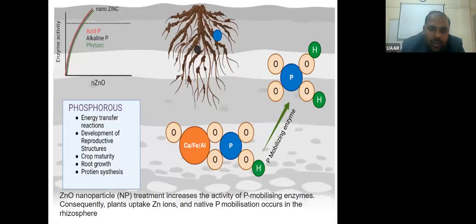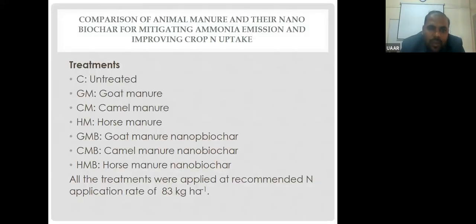In another experiment, in this experiment and another result, they also improved plant phosphorus uptake, because nanoparticle, especially the zinc oxide nanoparticle, they enhance the P-mobilizing enzyme activity, and consequently plant uptake of zinc and also the P-mobilization, and as a result they enhance the P uptake of the plants, energy transfer reaction and development of reproductive structure, and all the P activities they increase. So this also happened.